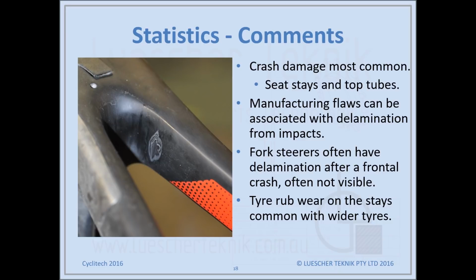So as I said, crash damage is the most common, and seat stays and top tubes are probably the most common areas of damage. And there's a number of reasons for this. Those tubes are quite light structurally, so the loads in those areas are less than other areas of the frame, so the wall thickness is thinner, and so they can be damaged easier. Also, those tubes are quite exposed, like the top tube. The handlebar will swing around in a crash and impact the top tube, or a seat stay is quite exposed. So those areas tend to receive the worst of it.